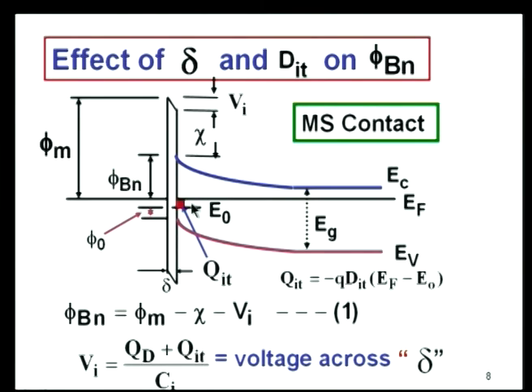What is E_f minus E_0? Take a look at this band gap. I have assigned this quantity as phi_bn, and this quantity below E_0, up to this point, is phi_0. See, below E_0 to that band edge, that is phi_0, and that quantity is phi_bn. So, we have got E_f minus E_0 equal to E_g minus phi_bn minus phi_0. So, from the total band gap here, I subtract this quantity and that quantity, I am left with this quantity. So, the charge in that gap is equal to minus q D_it into (E_f minus E_0). I am putting it as negative because they are acceptors. So, that is why I put it as negative.